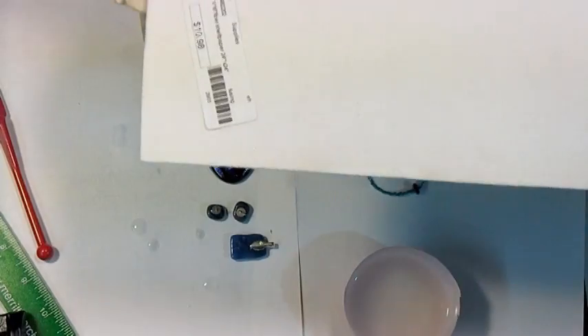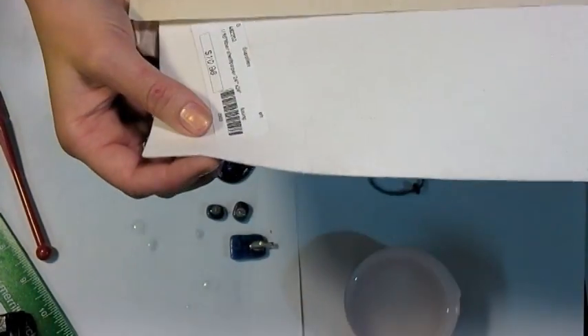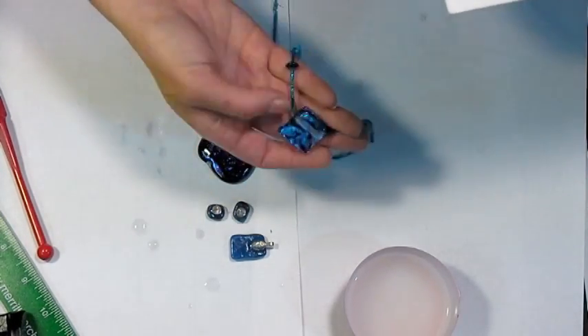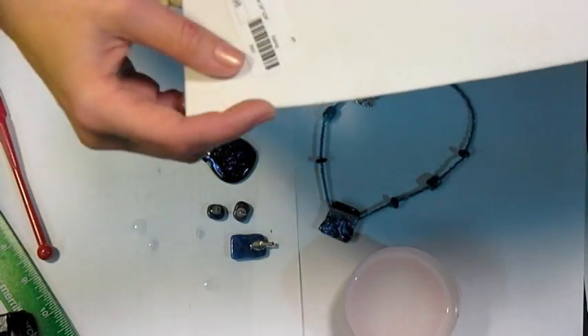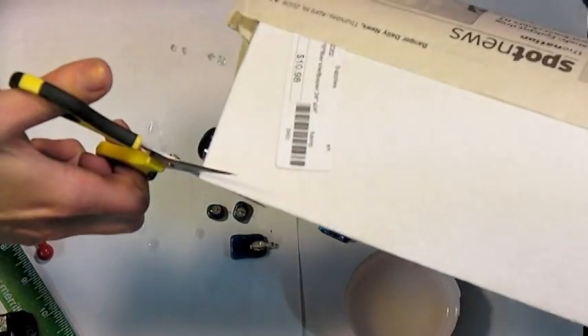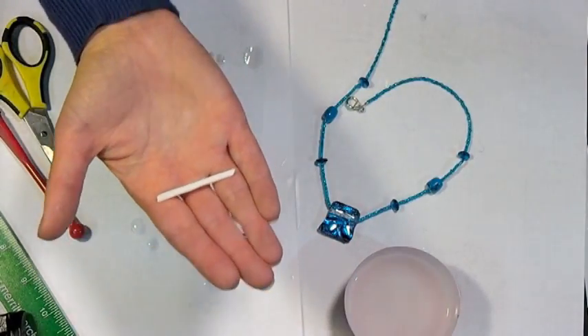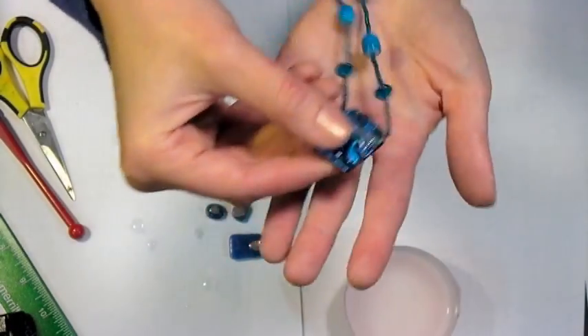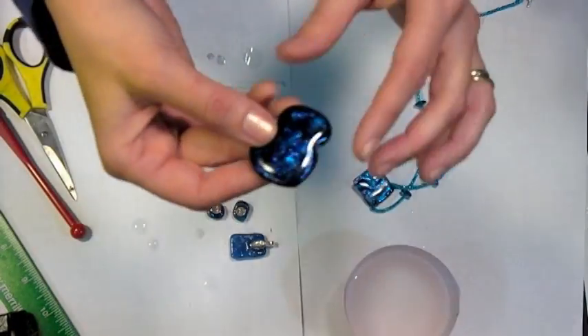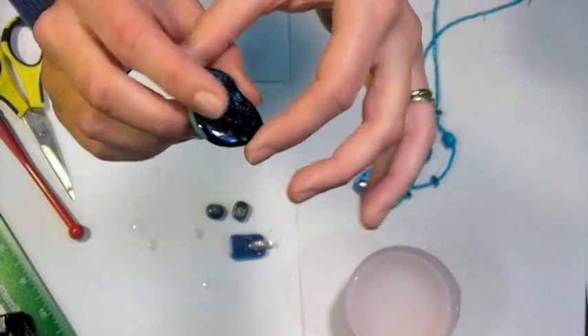Before you go, I want to show you what kiln paper looks like. It's rolled up in a tube — about 24 by 24 inches. This is 1/16 inch fiber shelf paper and it's quite thick. This is what I use when I want to put a string through a bead. If I want to make a bead I can put on a necklace, I'll cut a sliver off this paper — about as wide as I'd want my wire to be — and layer it between my layers of glass. That gives me a space to put a wire through. On one bead I did it between a clear layer and a black-and-blue dichro layer so you can actually see where the wire goes. On another I did a layer of light blue, then black dichro, then clear, so the hole is hidden underneath the dichro layer and you can't even see where it is.